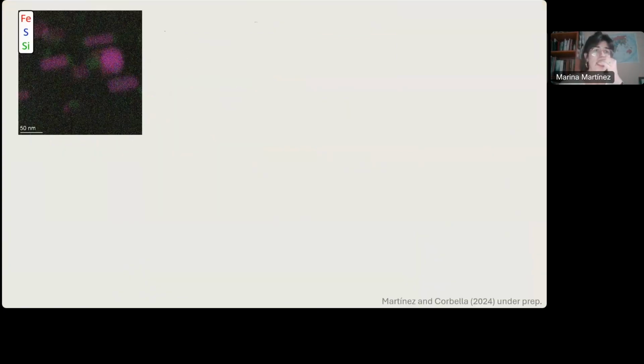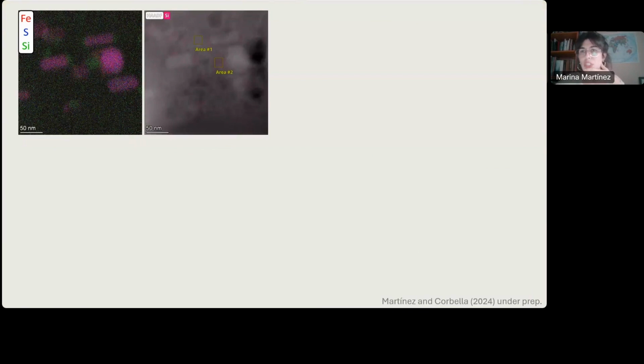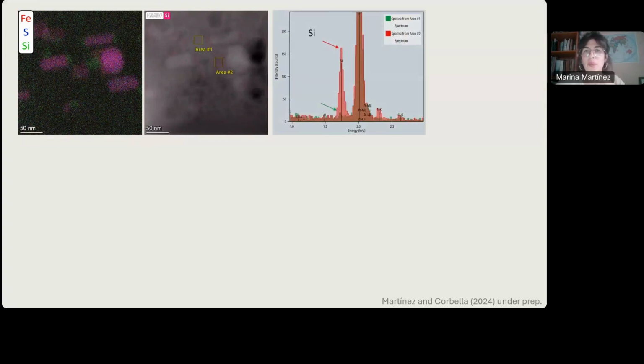Then I did these X-ray compositional maps at Goethe University in Frankfurt with Sherry, and we saw that we detect silica. I didn't detect that at my university because the instrument is not as good. And in here we saw some enrichment in silica that was not exactly where the inclusions were, but surrounding them, kind of associated with them, but not in the inclusions. We saw that the silica was real. There's a clear increase in silica in some regions.